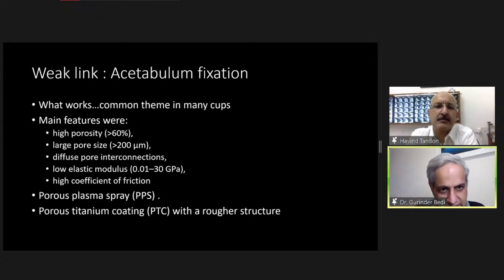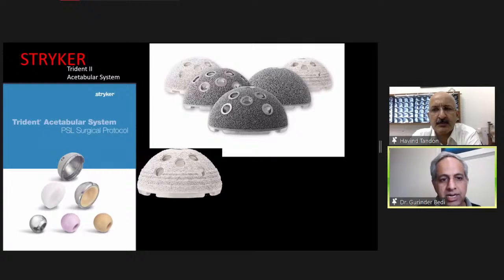So what works presently is what we're talking about. High porosity, more than 60%, large pore sizes. The pores should even have interconnections. Low elastic modulus: you want an elastic modulus comparable to that of the bone, and you want a high friction. You can almost scrape your hand with the cup. That's the kind of thing. And you've got these two kinds of roughened surfaces, whether it's a porous plasma spray or a porous titanium coating. I'm going to talk a little bit about that as well.